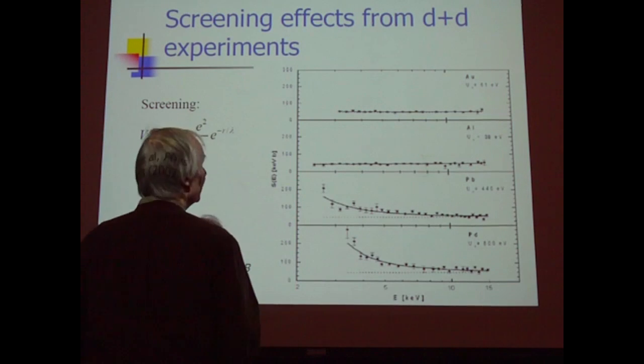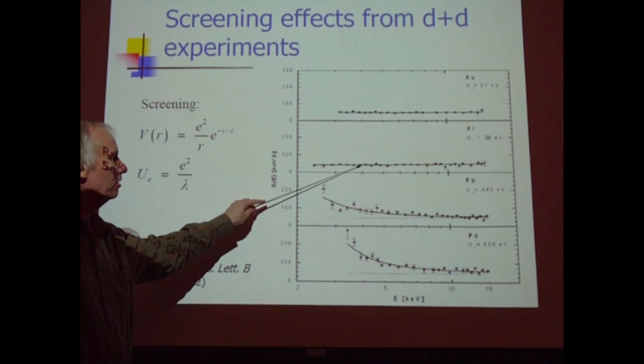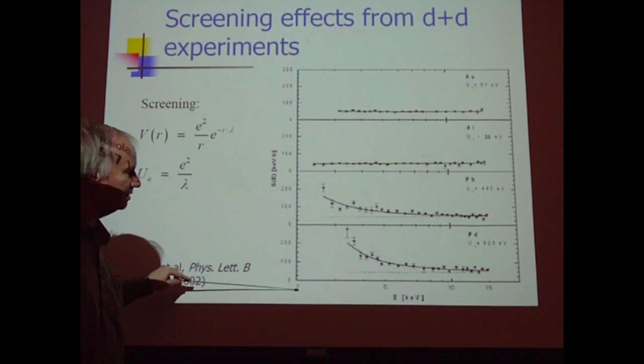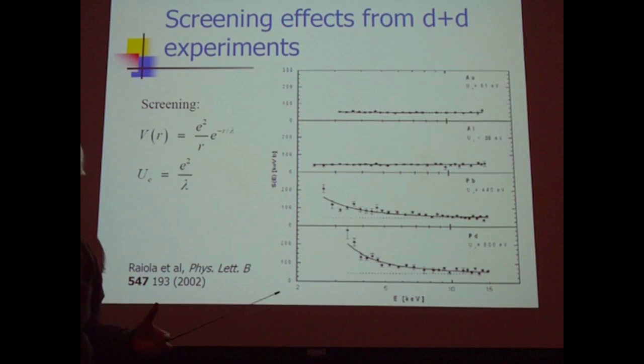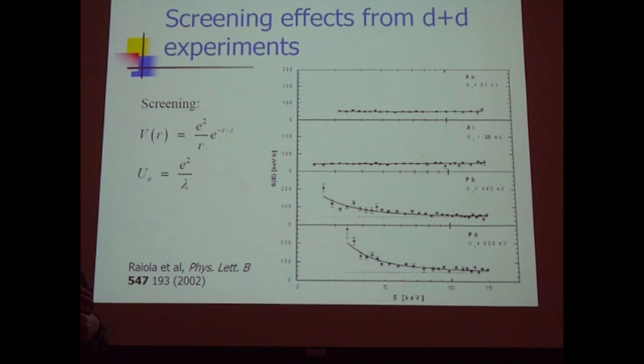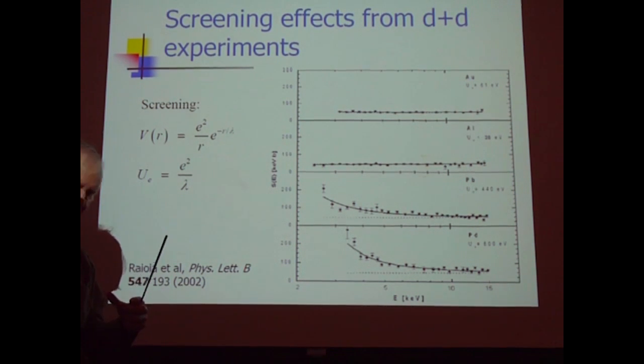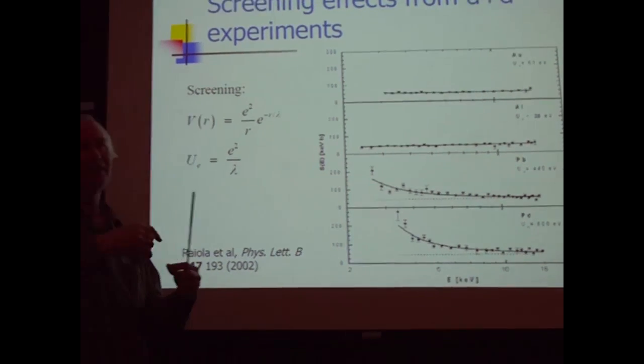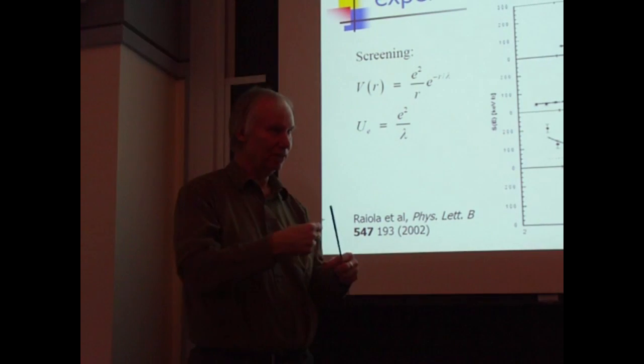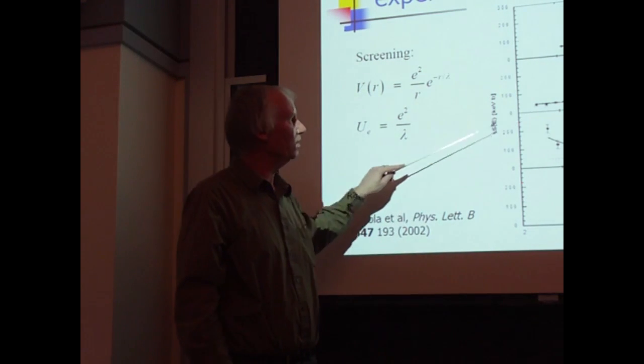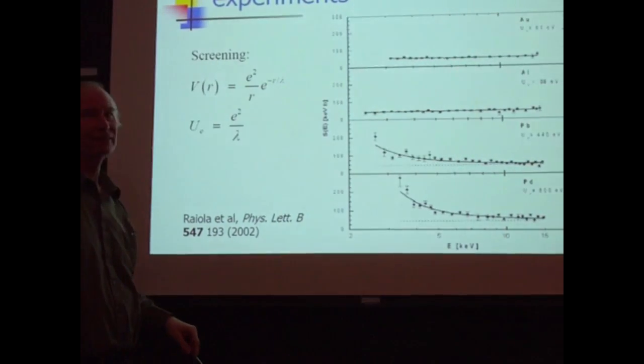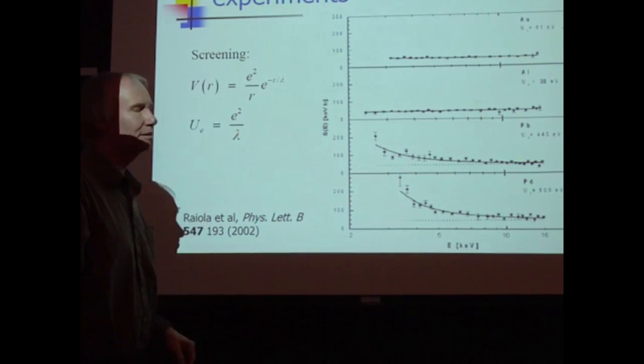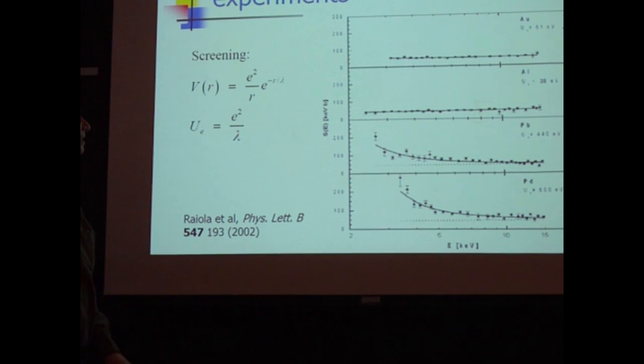What you see, for example in aluminum, is plotted against energy: 2 kiloelectronvolts, 5 kiloelectronvolts, 10 kiloelectronvolts, 15 kiloelectronvolts. These are low energy deuteron beam reactions. In the case of aluminum, the deuterium in the beam comes in and plants itself in the aluminum. Another deuteron comes along, and you get a fusion reaction. In this particular case, it's plotted in terms of the S factor, and the S factor is flat if there's no screening effects. Basically, you take the cross-section and take out all the obvious energy dependence. Whatever is left is what you're looking for.